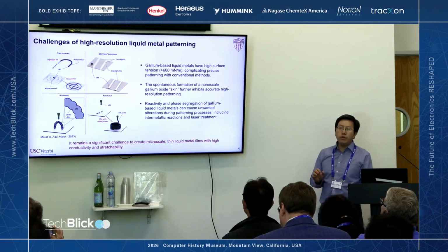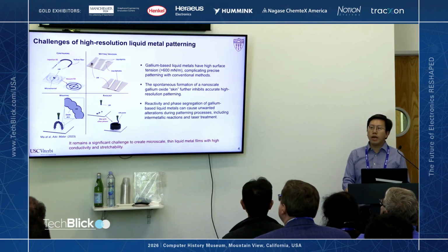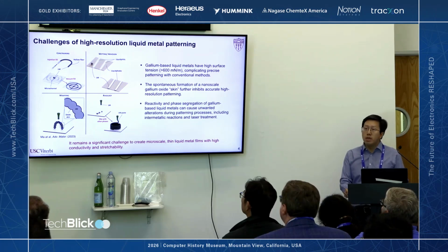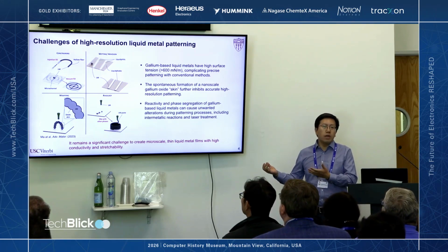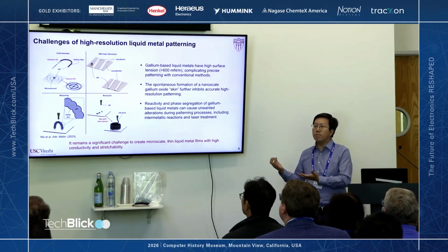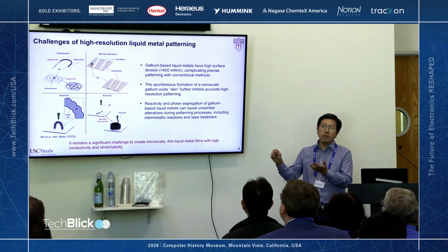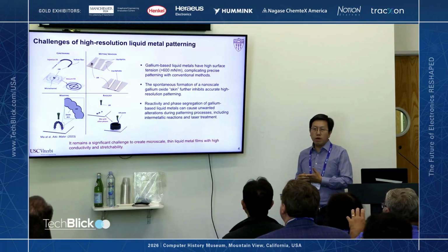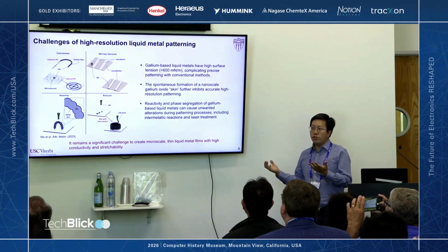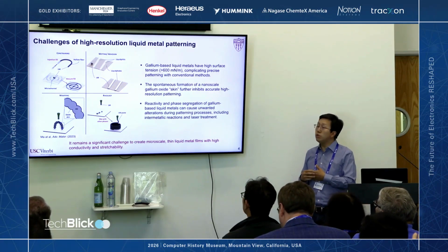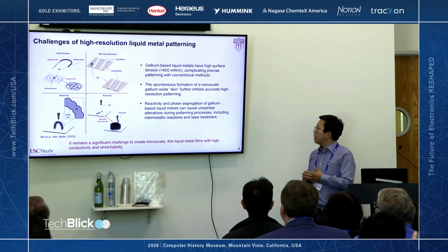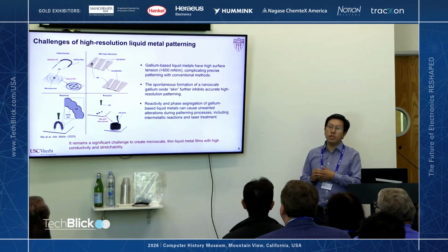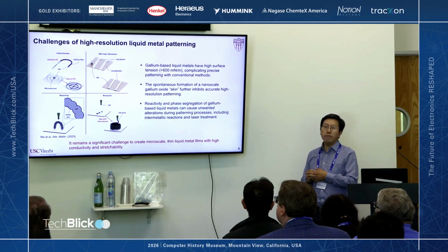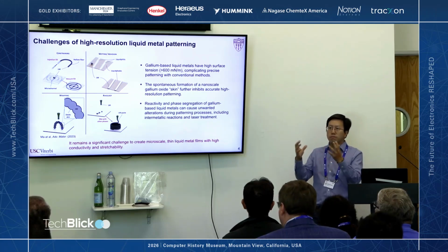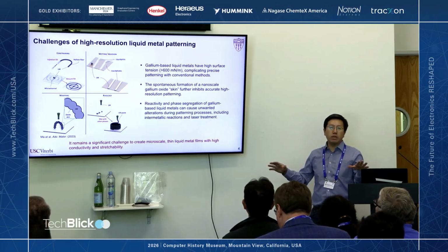In order to use liquid metal in stretchable electronics, one challenge we have to overcome is to pattern them at micro nanoscale resolution. We can do this easily with traditional conductors like copper and gold because we can use vacuum-based technology to deposit nanoscale thick thin films. We can use photolithography to achieve micro nanoscale resolution, but it's very hard to do so for liquid metals because first of all, it has extremely high surface tension. It's about 10 times the surface tension of water. So it tends to puddle or bead up instead of forming a nice thin film.